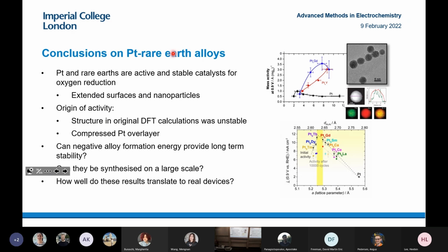So this is the conclusion on the platinum rare earth alloys part of my talk. They were active and stable for oxygen reduction. We showed this both in extended surfaces and nanoparticles. I think the important thing to bear in mind is that the structure in the original DFT calculations was not actually stable. When you model, you can put a lot of unstable structures into a DFT calculation and get what would be the activity, but that structure is not always what was actually formed under reaction conditions.